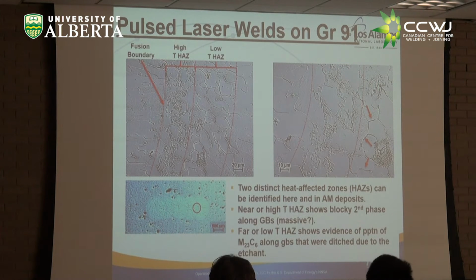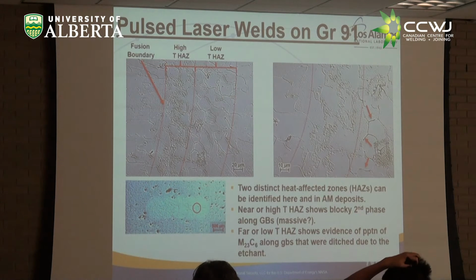So how did I reckon what was going on, the two funny regions we saw, the featureless region and the speckled region? I was able to conclude how those developed by taking one of the deposits, and I put, you can see here, overlapping laser spot welds. And then looking in the overlap region at these things here, you can see now the problem with looking at that one microstructure when all those were together. Were those featureless region and the speckled region formed as I was making that little weld pass, or were they formed later when that weld pass became the heat affected zone of all the ones around it? Couldn't tell. So this was meant to spatially isolate what was going on.